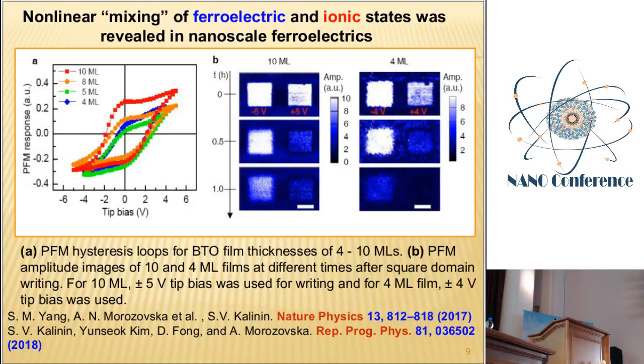Well, here are our results, better to say, results of our experimental collaborators from ORNL. And in those results, you can see that you have a very, very thin barium titanate film. Barium titanate is a proper ferroelectric, and its typical critical sizes are rather high. It can be microns in accordance with the earliest results. With the latest results in hand, it can be hundreds of nanometers.